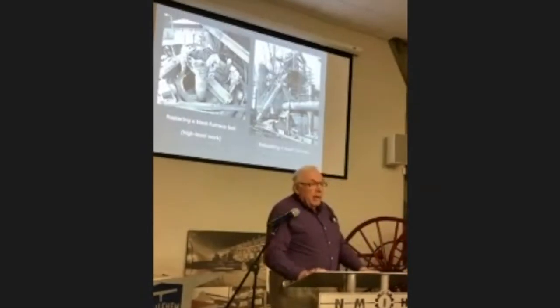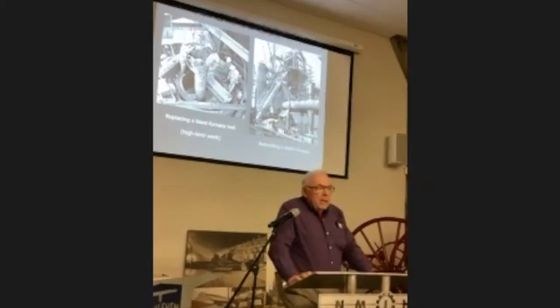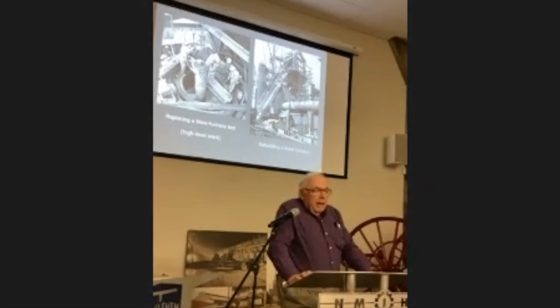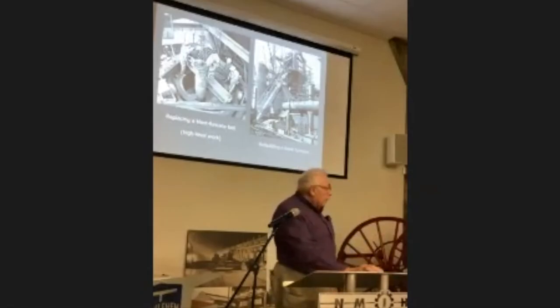And in colonial eras, furnaces generally ran seasonally. You'd fire it up in the fall and it'd go out of service in the spring because it was just too hot in the summertime. And finally, we got to where we could run a furnace around the year, and then a year was a campaign. And when we finally got to the 1860s, when this place opened up, we still had a year or maybe a year and a half. And by the time this place shut down, a campaign on the blast furnace might be 12 or 13 years. So it just shows how we improved things as we went forward.